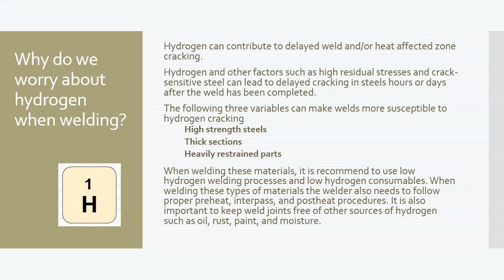So, why do we worry about hydrogen when we're welding? I'll boil this down. Because hydrogen gets dissolved into the weld metal and it's trying to look for a way out. And as the weld cools and the metal cools, it doesn't have that quick transit to the surface. Hydrogen travels or swims through solid metal a lot quicker when the material is warm. So that's why we're talking about post-weld heat treat and preheat. This helps the hydrogen escape.